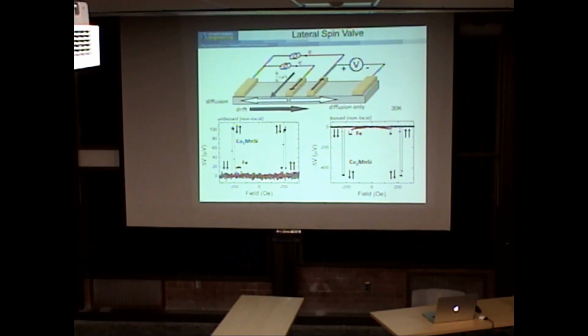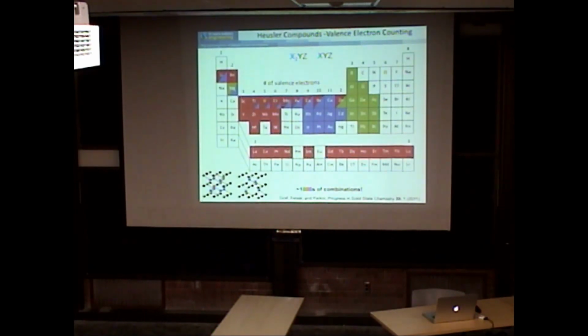Okay, another thing that Paul Crowell's been doing is putting a bias on the detector. It can change the sensitivity of the detector. So if you go with a bias detector, you nearly go up by over a factor of 4 in the signal level that you've got. Now you can see immediately that cobalt-2 manganese silicon was a much better spin injector than the iron was. And iron before this was our highest spin injection efficiency. Okay, so now let's come back to this thing.